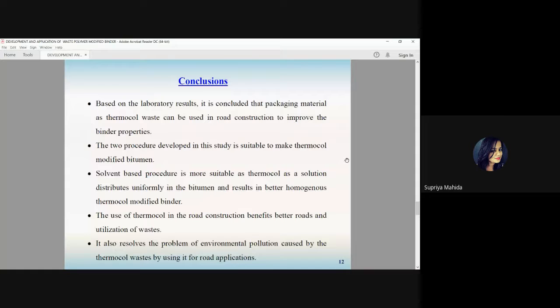So based on all these experimental results, it is concluded that thermocol waste, which we used as a packaging material, can be easily and effortlessly used for road construction to improve the properties. We adopted the two procedures developed in the study, and both are suitable to prepare the modified binder. We concluded that the solvent-based procedure is more suitable as it is very easy to add, uniformly distributed, and gives a better homogeneous thermocol-modified binder. The use of thermocol in road construction benefits the roads, utilizes the waste, and also resolves the problem of environmental pollution caused by thermocol waste.